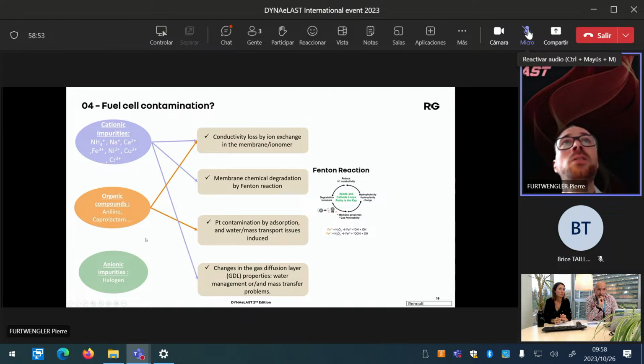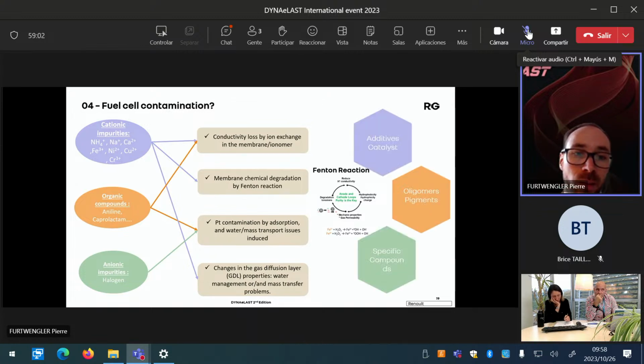And the last category I will show you here is the anionic impurities. Anionic impurities such as the halogens, for example, which are coming from specific compounds. We will also have interaction with the catalyst. So here, my big message to you is that in case you want to use TPE for fuel cell, what is very important beyond all the conventional aspects, which are the mechanical properties, does it work, doesn't work? Well, we also have to think about the contamination of the fuel cell, and the contamination is often happening with the material leaching ions because of the water, because of the flux of water inside of the hoses.